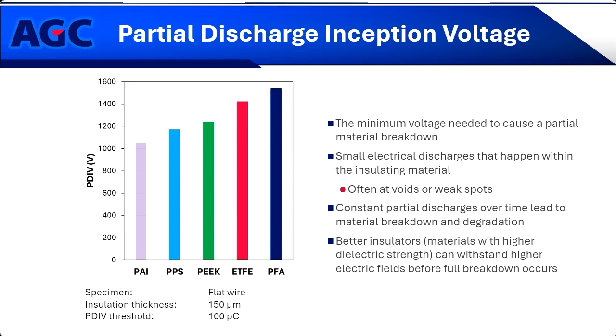Usually when you're performing these tests, you will set a specific threshold and say, once there's enough electrical activity past this point, that's the partial discharge inception voltage. So at what voltage is that threshold passed? Partial discharges are small electrical discharges that happen within the insulating material. This is most commonly at voids or weak spots.